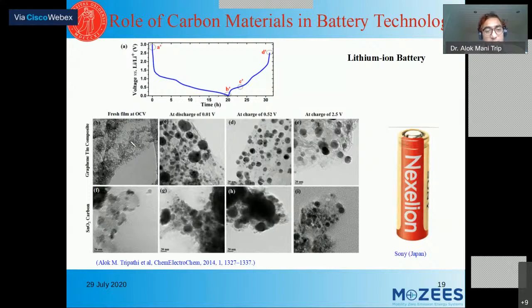We have seen these are our first electrode material. These are graphene supported with nanoparticles of tin. When it was lithiated, when lithium started going inside, one tin particle generally takes 4 lithium, which means you can count that the volume will increase.